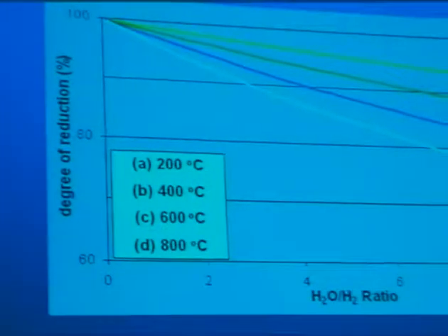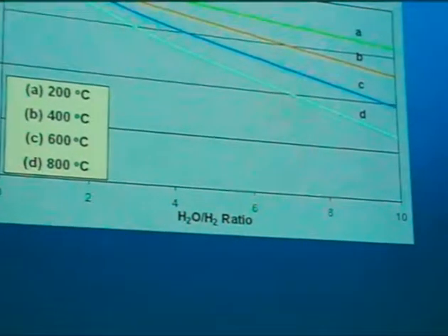If you look at the thermodynamics of the reduction of cobalt, and calculate this at various water to hydrogen ratios, which is what you're basically getting in a reduction scheme, let's push it all the way up to 10. Well, you're never going to operate a system with that high a ratio of water to hydrogen. You're going to be operating down here at worst.